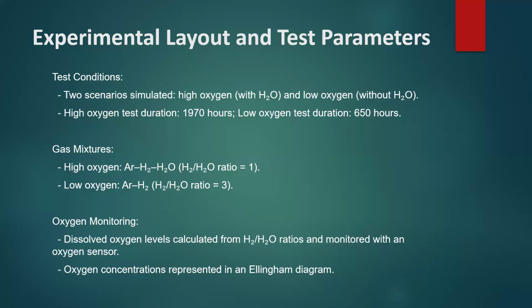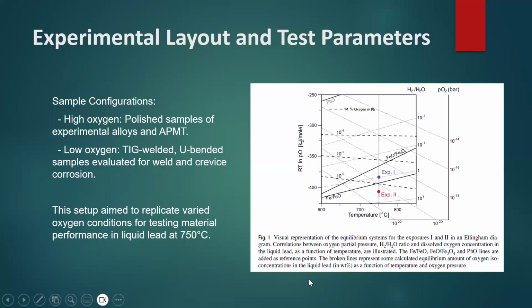Oxygen monitoring involved dissolved oxygen levels calculated from the hydrogen to H2O ratio, monitored with an oxygen sensor, with oxygen concentration represented in an Ellingham diagram. This shows the visual representation of the equilibrium system for exposure 1 and 2 in the Ellingham diagram.